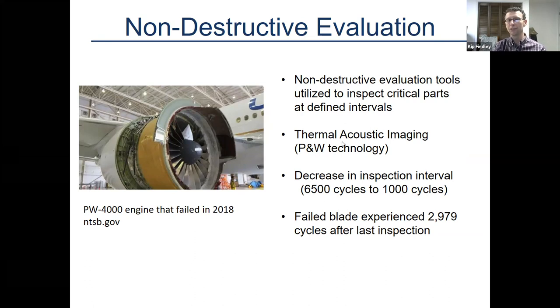Thermal acoustic imaging is basically where they send a sound wave through the part, and that sound wave causes friction. So if there's any open surface within the part, it causes friction, and when it causes friction, it causes heating. Then this imaging technology can detect that heat and figure out if there's a flaw there. It's a pretty interesting thing, but technicians have to be highly trained and very careful in doing this to make sure they don't miss something.